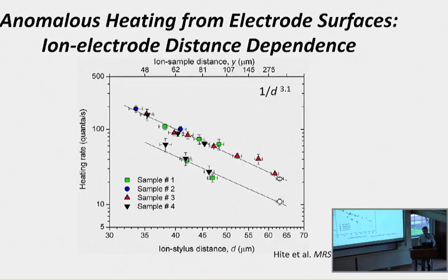So we tried to think about what's the difference between an ion trap that's grounded and an ion trap that is operational. And I could only think of one thing, that the RF was playing a role. And remember, we saw in that Arrhenius curve that temperature was so low, it was as if temperature wasn't enough to cause surface diffusion. It's as if the RF fields or currents or something like that are driving the adsorbates on the surface to move around faster than they would normally.